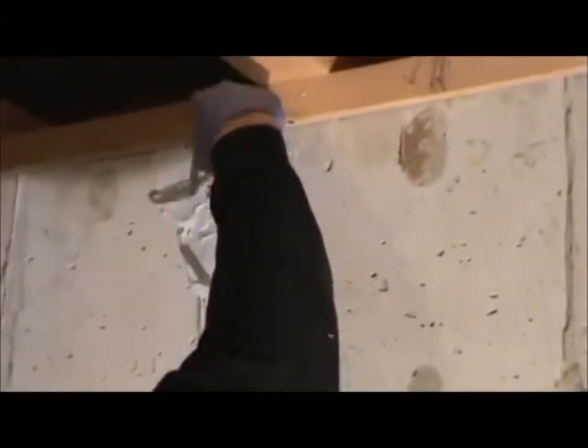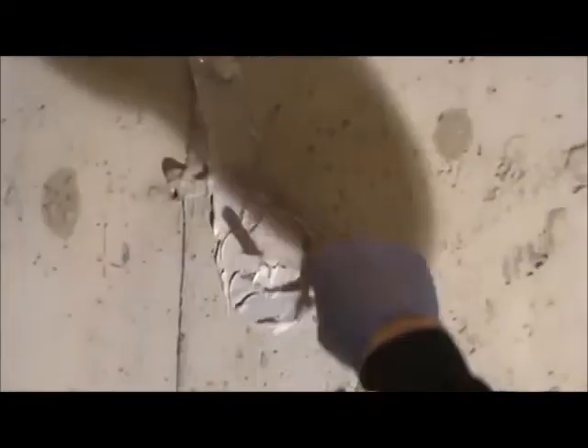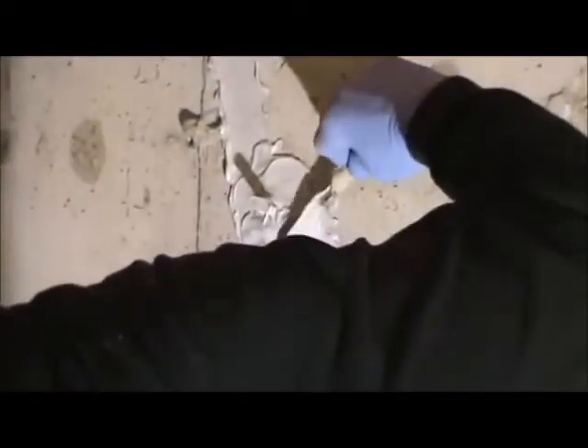After the ports are placed, additional batches of epoxy paste are mixed to seal the crack and around the ports. Normally, the top 1/8 inch of the crack is left unsealed, and you're going to see why in just a couple of minutes. Any portion of the crack above ground level will also need to be sealed on the outside of the foundation. Surface seal's only purpose is to hold the epoxy resin in place until it hardens.